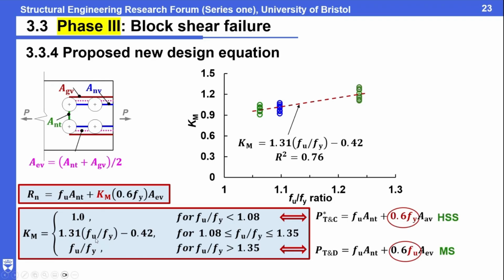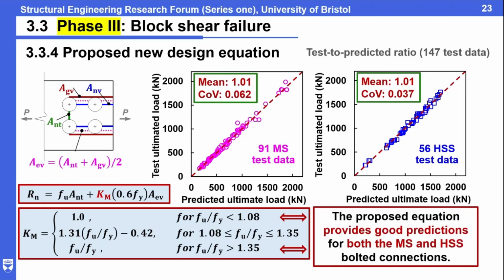We want to have a universal design equation to cover the mild steel and high strength steel block shear failure. Then this is the development of the value of the factor, and then it needs validation, right? So for validation, we based it on the 147 data from literature to do the independent validation. So we can find that it works very well. For mild steel and high strength steel, both can provide a very good prediction. So this is our equation.